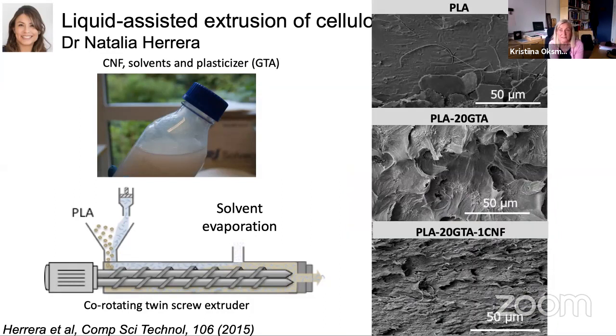And here is just an example of how these materials' fractured surfaces look. If we look at pure PLA, you can see quite a brittle fracture. And then when we have added 20% plasticizer, this fracture is getting very tough. So the material is getting much tougher. And when we are adding 1% cellulose nanofibers, again, this fracture surface is quite different, but we are still having good toughness left.